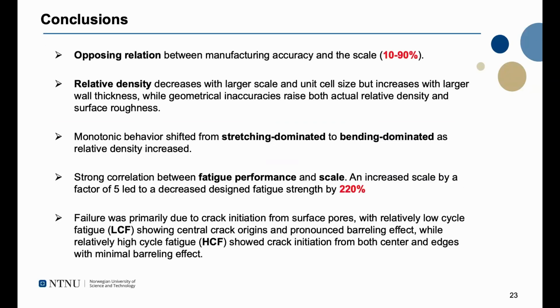So in conclusion, an opposing trend between the manufacturing accuracy and the scale was observed in the range from 10 to 90%. That's quite a lot. The relative density decreased with the larger scale and unit cell size, but increased with larger wall thickness. And the geometric deviation increases for both relative density and wall thickness. The monotonic behavior for static compression also shifted from stretching dominated to bending dominated.